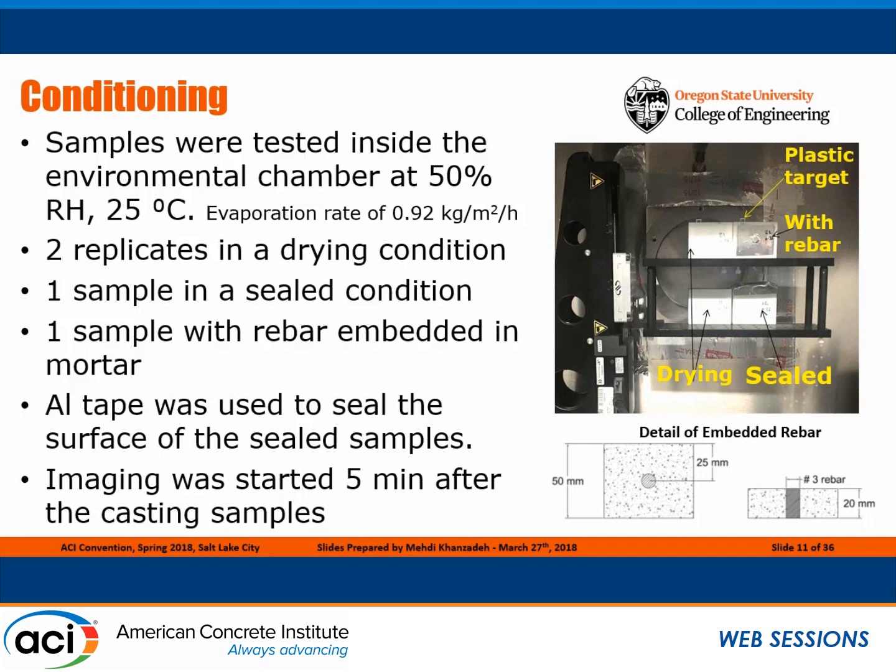Imaging was started 5 minutes after casting the samples. We also had plastic targets at the surface of the samples in order to trace the movement of the plastic targets and compare it with the settlement of the surface of the sample.